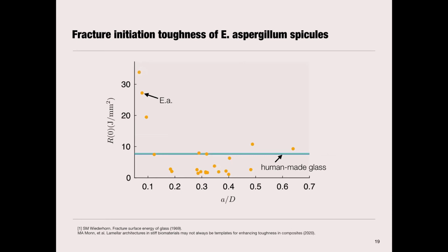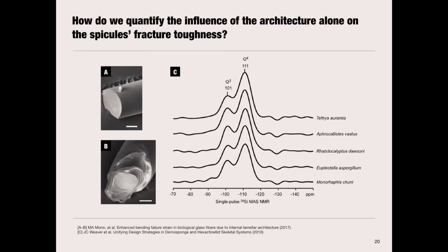So I stopped here, which is really where I was getting to the idea that we need some sort of a metric to compare this material to. Because at this point, I've been showing these lines for human-made glass, but really this isn't just standard glass. It's chemically fairly different. It's partially condensed silica. So that means that it is not just SiO2 fused silica. It also has some end groups, like some hydroxyl groups. You can see that in this single pulse silica NMR spectra.